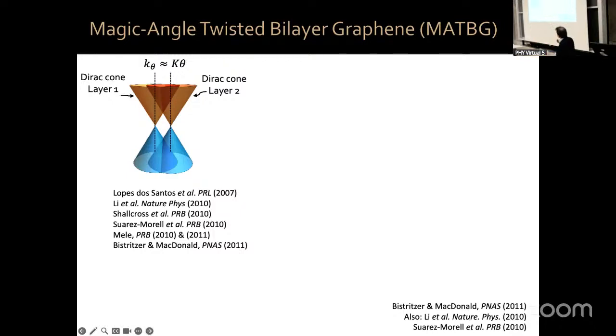This is the Dirac cone of layer 1 of graphene, and this is the Dirac cone of layer 2, for a particular K valley. You can see that this would be the situation if electrons in one graphene sheet weren't aware that there is another graphene sheet - this would happen, for example, if the graphene sheets were very separated.